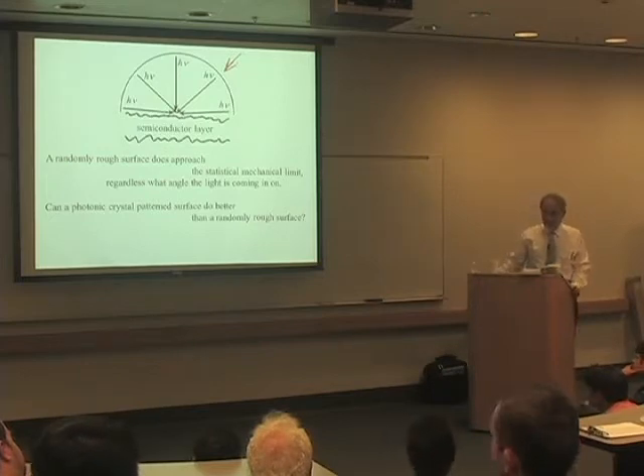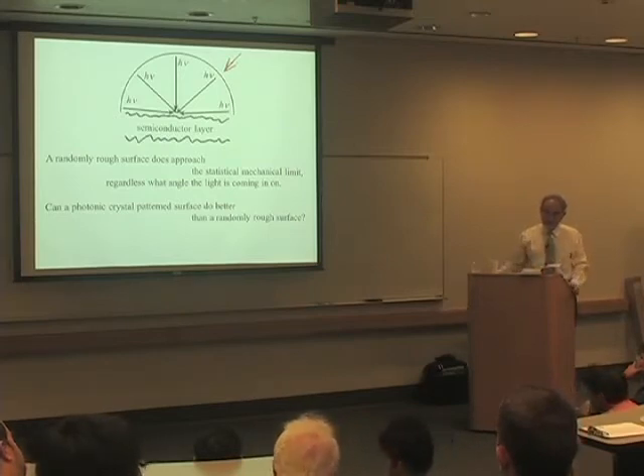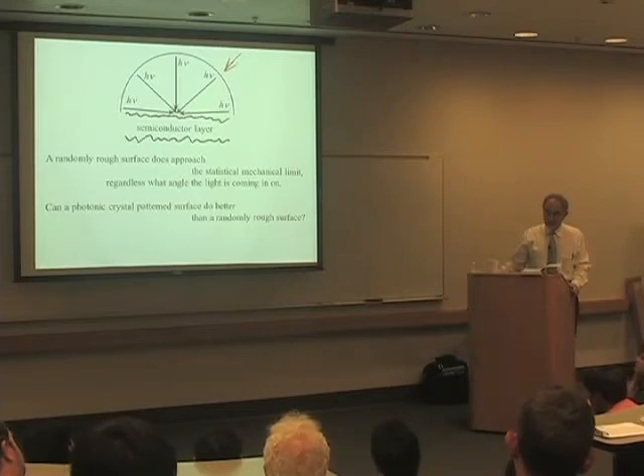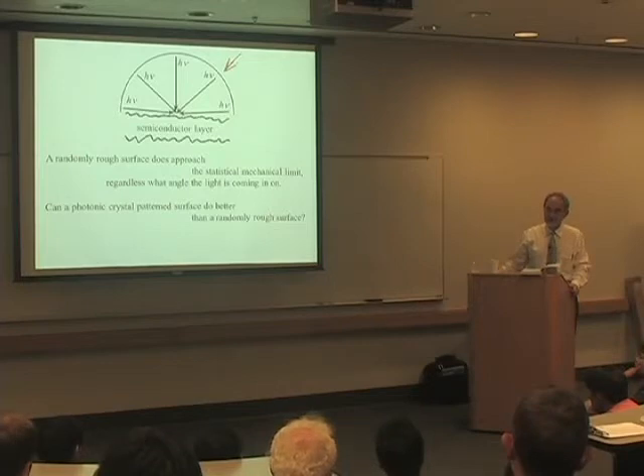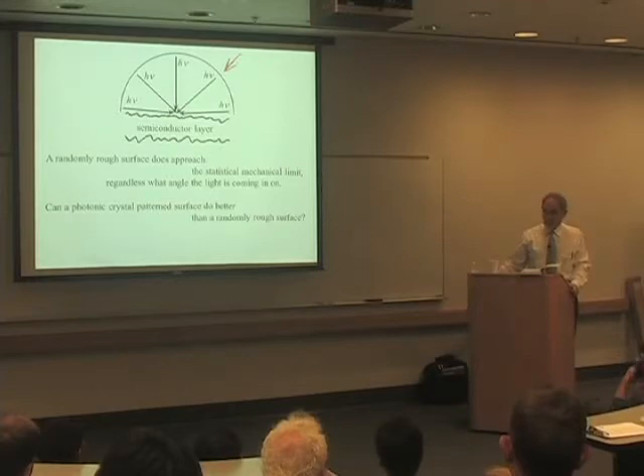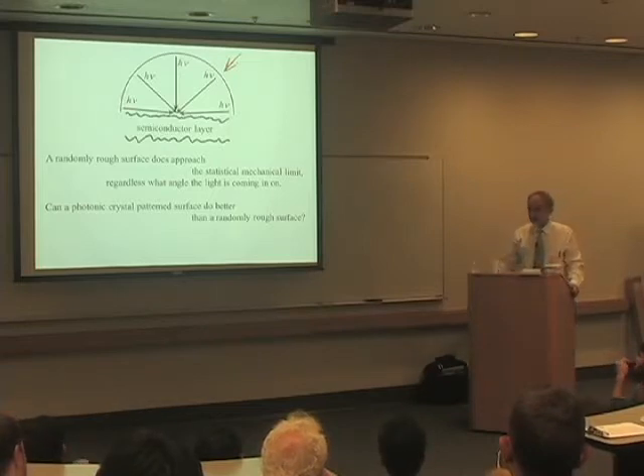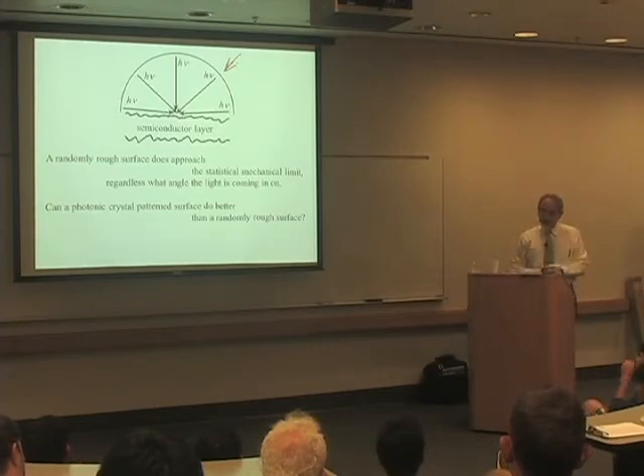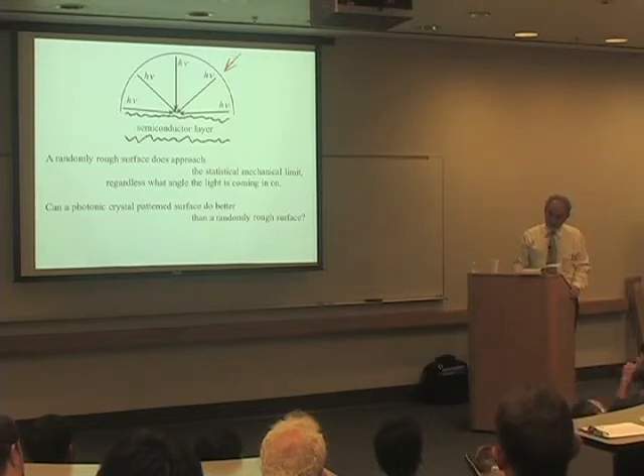So you have to do this in such a way that whatever texture or trick you put on it, you have to be able to accept light from all angles. There's a very simple statistical mechanical argument that says you can never do better than a randomly rough surface. Nonetheless, since I proposed this almost 30 years ago, there have been countless papers on how they're going to beat the 4n squared limit. They're going to have some kind of very clever geometry, but it almost always ends up that they've somehow restricted the acceptance angle for the sunlight.